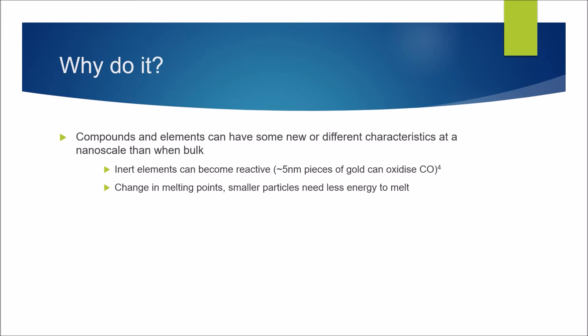An example of this as you can see is gold. At around five nanometers it can oxidize carbon monoxide. That just shows you how reactive it's become, whereas in bulk you can't even use it as a catalyst because it's just not reactive enough.